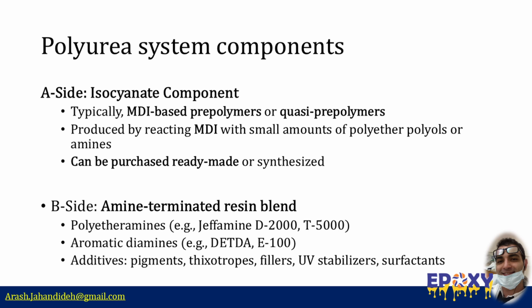The B side is the amine-terminated resin blend, which contains the reactive components that drive the fast gel time characteristics of polyurea. Common ingredients here include polyetheramines such as Jeffamine D2000 or T5000 for flexibility and elongation, and aromatic diamines like DETDA or E100 that serve as chain extenders and help achieve high mechanical strength. This side also includes a range of additives such as pigments for color, thixotropes for sag resistance, fillers for cost and performance balance, UV stabilizers to enhance weatherability, and surfactants for improved flow and wetting. Together, the A and B components create a highly versatile system that can be customized for coatings, linings, membranes, and more.